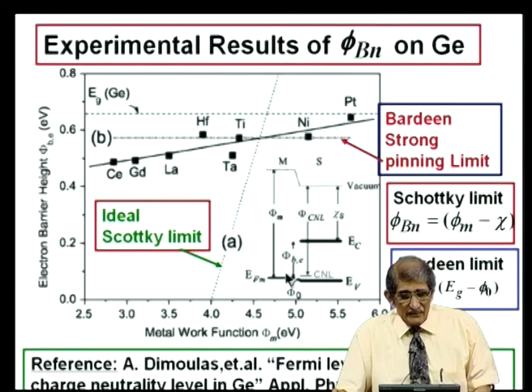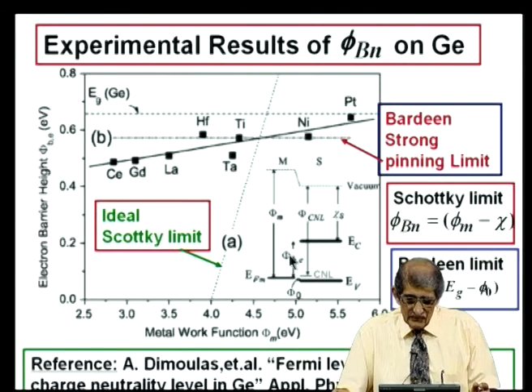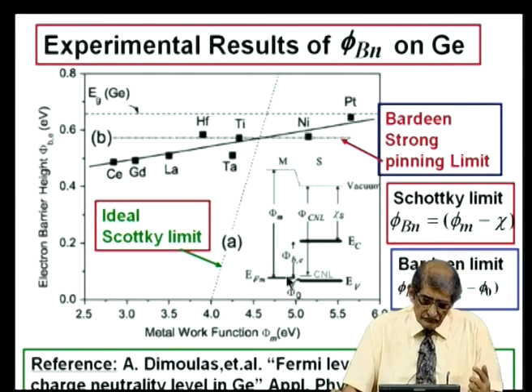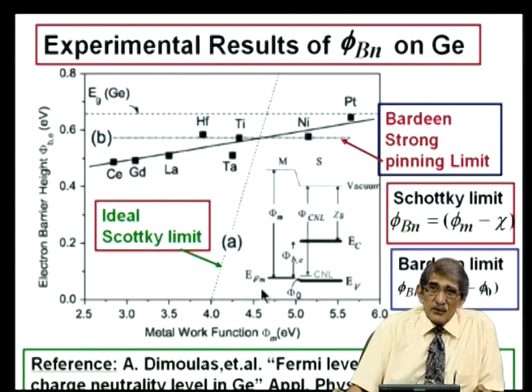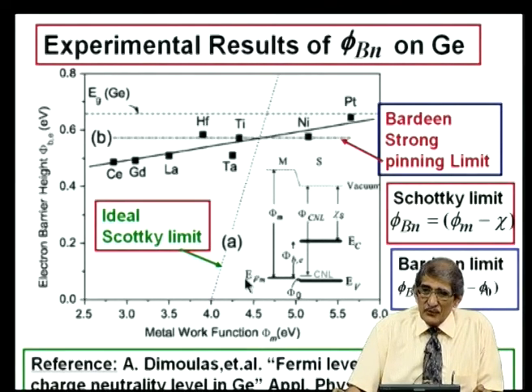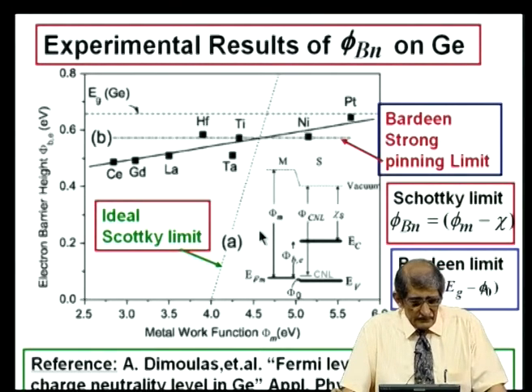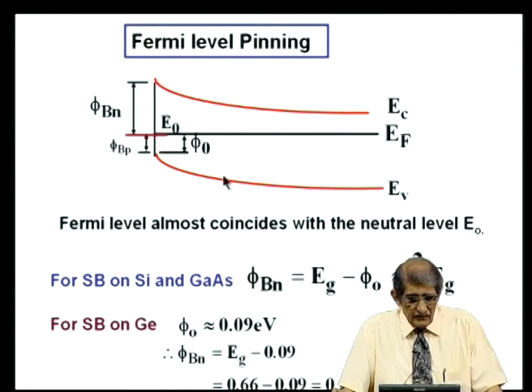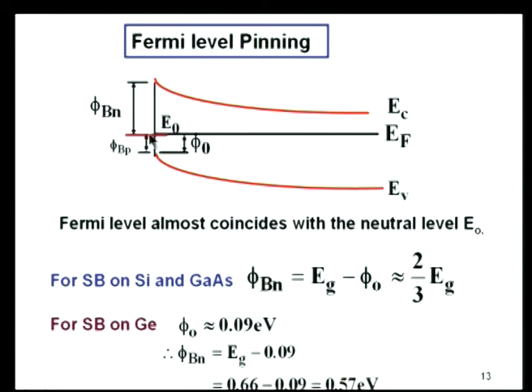So, it will be very easy to make p channel MOSFETs with metal semiconductor contact on germanium. That is good news for people who want to make germanium p channel MOSFETs. So, if you want to get an n channel MOSFET with germanium or silicon, you have got to do something else. Okay. So, that is what the situation is there. This is the Fermi level pinning which I was talking of. In the case of gallium arsenide, etcetera, phi_bn is 2/3 of E_g. In the case of germanium, phi_0 is 0.09, therefore, phi_bn is about 0.57.